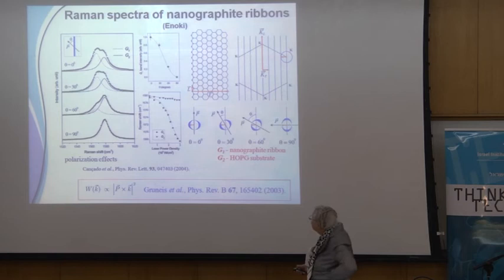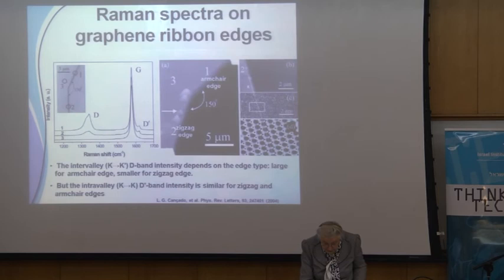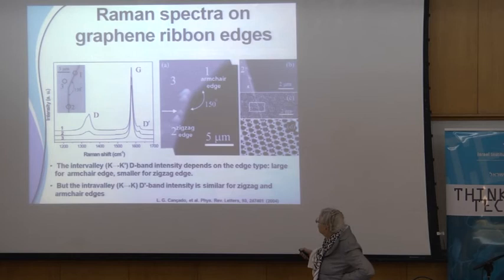And so we do polarization experiments and all that, so we can do the spectroscopy. That's just to show you. The interesting thing for the band gap is that the armchair edge and the zigzag edge can be easily distinguished by spectroscopy. So we don't have to touch the sample. The samples are very, very tiny. They're only nanometers in size. But if you can shine light on them, then we can probe them.